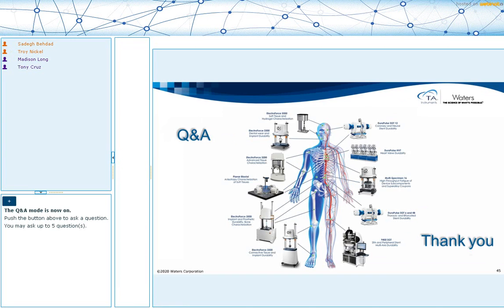So the questions here are, let me take one here that says, can I change the loading level after my test started, or do I need to stop and restart it? Yes, you can change the load level as your experiment is going on, because we know that when you want to create the sine curves, it's important to maintain the stress level for the whole duration. As you're exposing this material to stress, you start to generate micro cracks or small failure points inside it before it eventually breaks. So you see a decrease in the stiffness with time.